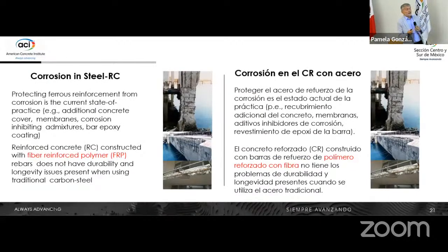I mean, kind of obvious, like I already mentioned it. We have used many ways to slow down the degradation of reinforced concrete. We have looked at additives. We look at additional cover. We put membrane. We have coated the steel, but corrosion unfortunately happens, right? It happens because we have the chlorides entering the concrete. It happens because we have carbonation of the concrete and all these reasons, okay?